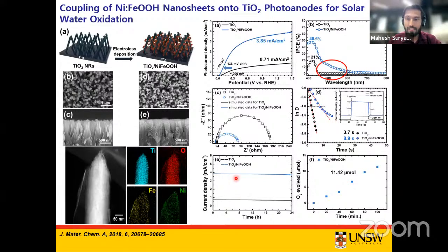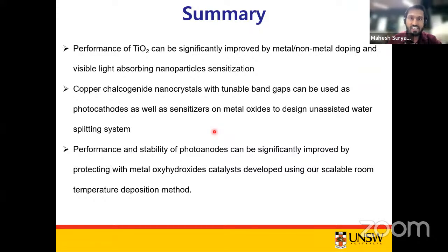But notably, if you see the stability plot, we carried out the stability test for 24 hours after decorating this NiFeOOH catalyst on the TiO2 nanorod arrays, and you can see that there is not even a 5 to 10% decrement in the photocurrent density value, which suggests how effective these catalyst materials are in stabilizing these photocathodes or photoanodes, as well as improving their performance. So this is the final summary.